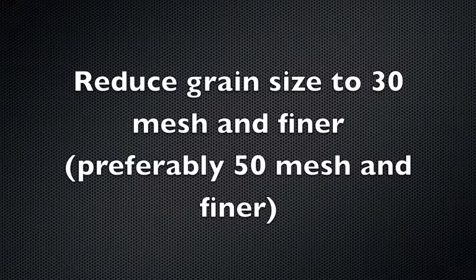I fire for 10 minutes at 1600 degrees Fahrenheit. This ensures that when you seal the material between the glass, there won't be any off-gassing to mess up the process. After you've pre-fired the materials you want to encapsulate, if they're not already fine, you need to reduce them to 30 mesh and finer grain size. Small ball mills are great for this. A hammer and pestle will often work as well. If you don't have any way to reduce the size, it's best to start with fine materials.